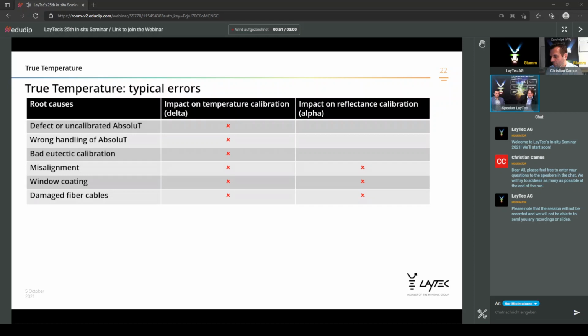A damaged fiber cable will have a direct impact on the initially calibrated transmissivity of this cable, possibly for both the light source cable as well as the detector cable. Such an impact on the transmissivity will have a direct impact on both the temperature calibration, the delta calibration, as well as the alpha calibration when you do reflectance calibration. Damaged fiber cables does not mean that the transmission is immediately cut down to 0%. It's more that the transmissivity is no longer constant and is fluctuating and is very sensitive to vibration or motion or even small hits.